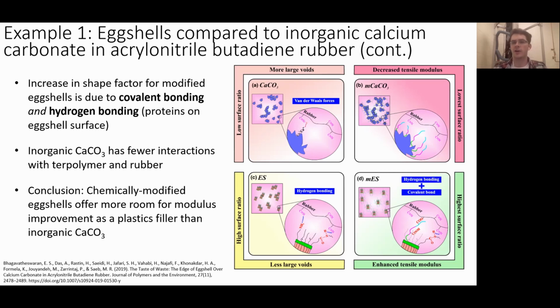Right, so you can see in this diagram down here on the right, they are stating that there were only van der Waals forces between the unmodified calcium carbonate and the rubber, whereas the chemically modified eggshells, they believe, actually promoted hydrogen bonding and covalent bonding between the functional groups on the eggshell surface, the chemical surface modification with the terpolymer, and the rubber itself. So there's a lot of bonding going on here.